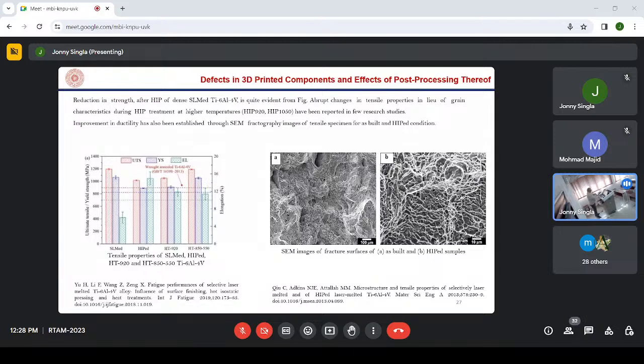This is a graph, and this is the SEM image which endorses why the ductility improves. This is after heating, and this is for as-built. If you see the morphology of the surface, it is clear that this is a ductile material as compared to this material. So you can say that heat treatment specifically leads to an increase in ductility. Here also, this is the as-built sample with UTS, yield strength and elongation, this is for HIP, this is for heat treatment at 920 degrees Celsius, and this is heat treatment for 850 to 550 degrees Celsius. Maximum ductility you can achieve with HIP treatment.